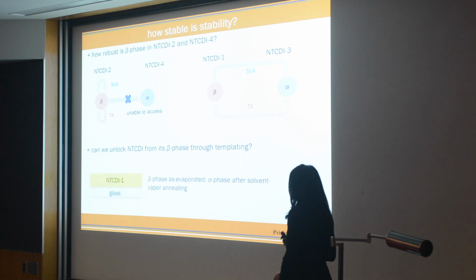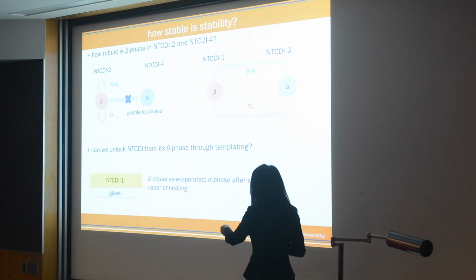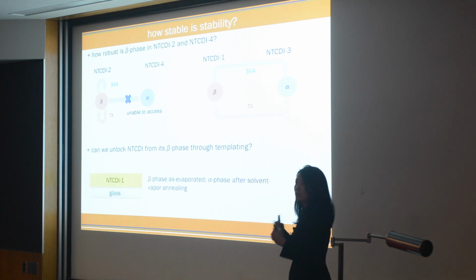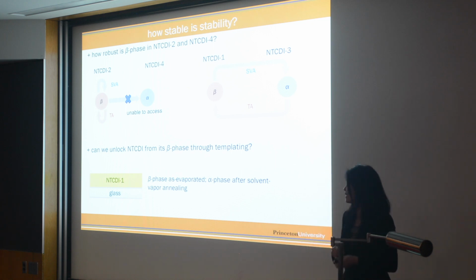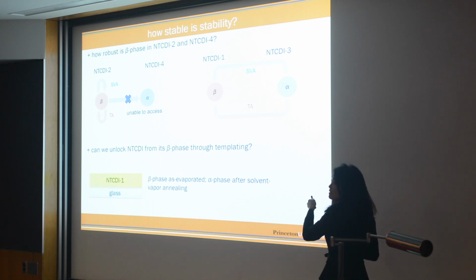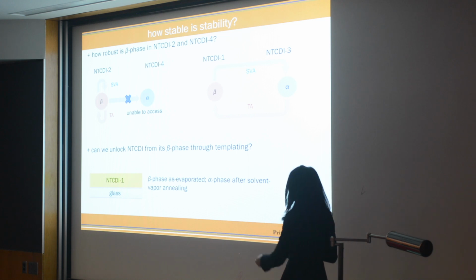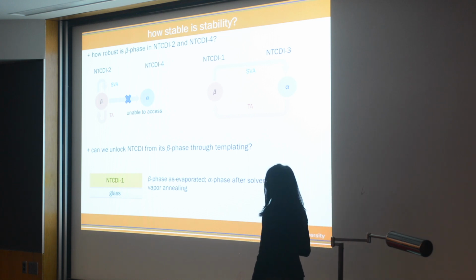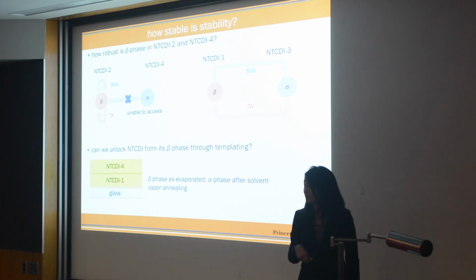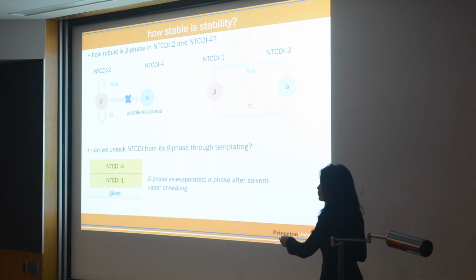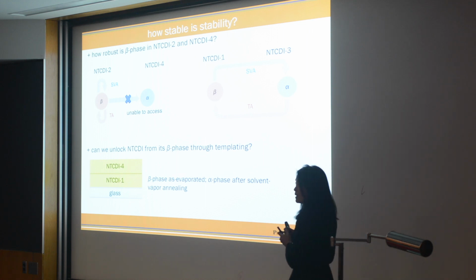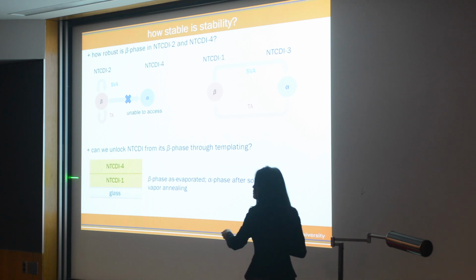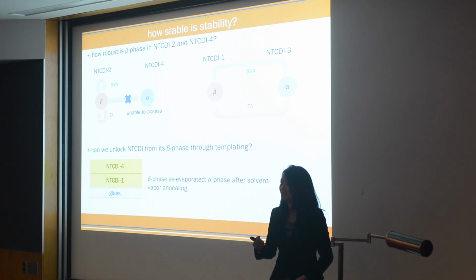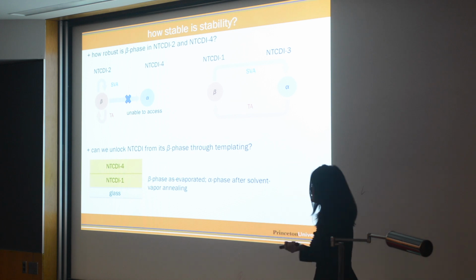So again, we conducted a very simple experiment. We put down NTCDI1. And when we put down NTCDI1, we access the beta phase. But we can solvent vapor anneal to access the alpha phase. So we have an alpha phase template. And now we're going to put down NTCDI4. Okay? Now, NTCDI4, previously, we were only able to access the beta phase. So the question is, in the presence of an alpha phase at the bottom as the substrate, can we now seed the growth of the alpha phase in NTCDI4?